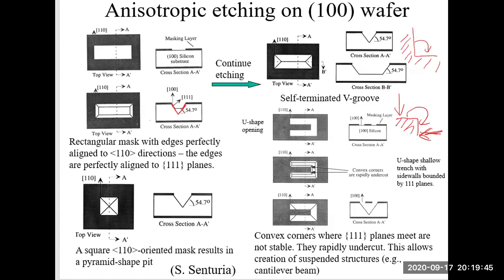It's very different from the concave corner, where the two 111 planes protect each other's side wall. So the concave corner is stable. The convex corner is not stable, so it will not last long in anisotropic etching. It will be undercut quickly.